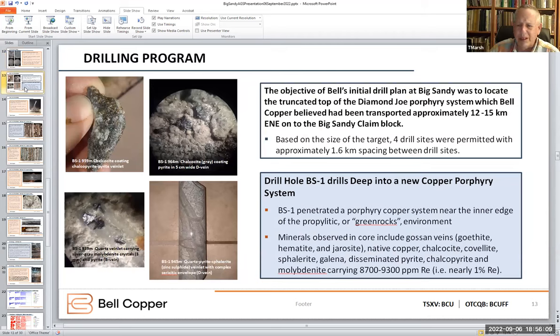Should be looking at slide 13. Drilling program, right? Okay. Yeah, so that's what we saw in that first intersection, once we got under the oxidation: chalcocite overprinting pyrite. Down in the lower left, some coarse molybdenite grains. These are about 3 millimeters across, very coarse, real flashy molybdenite grains. I sent those to Holly Stein at Colorado State University. She called back and said, "Tim, you about broke my mass spectrometer." They ended up running 8,700 and 9,300 parts per million rhenium, which is nearly 1% rhenium in the molybdenite. Globally, those are extraordinarily high rhenium numbers.